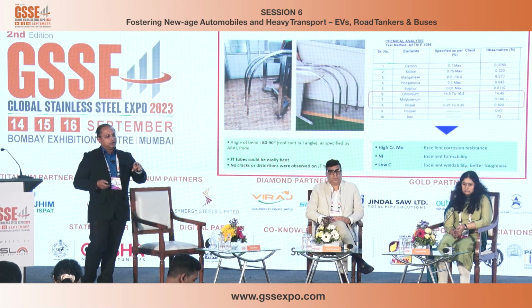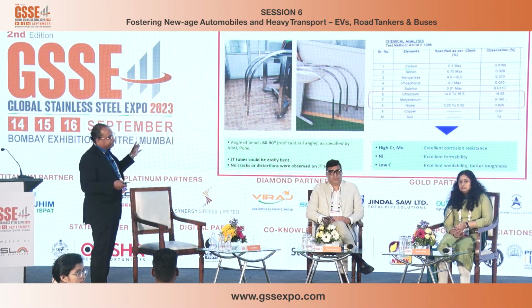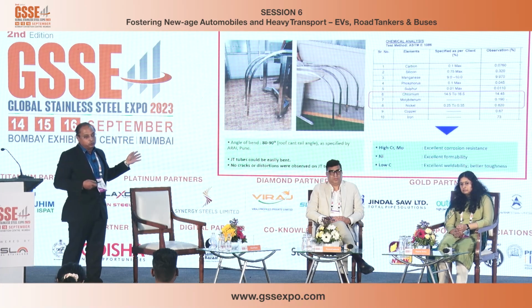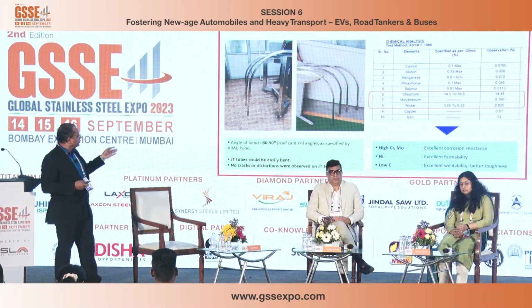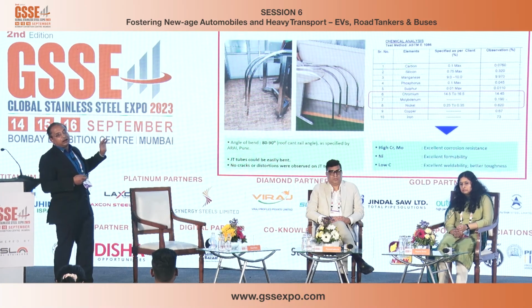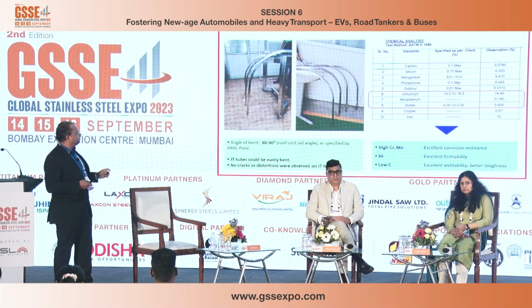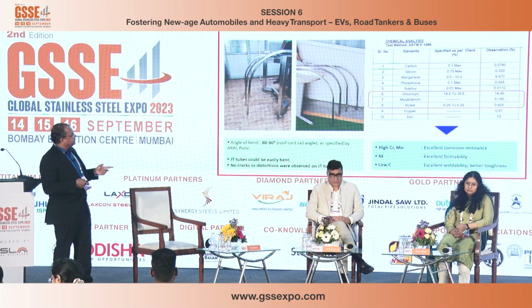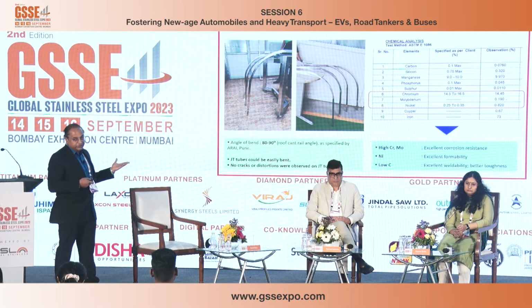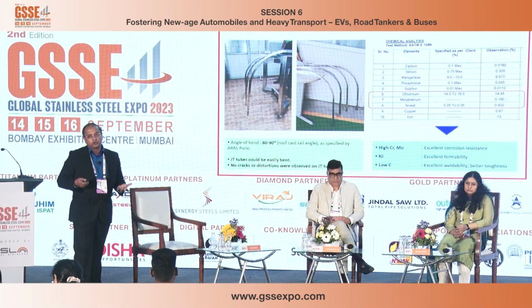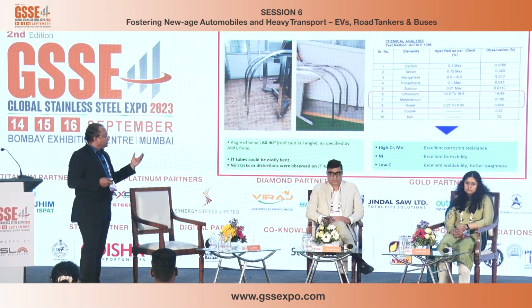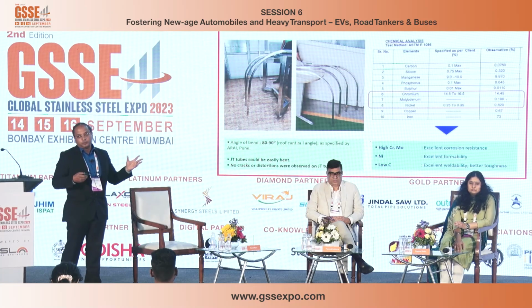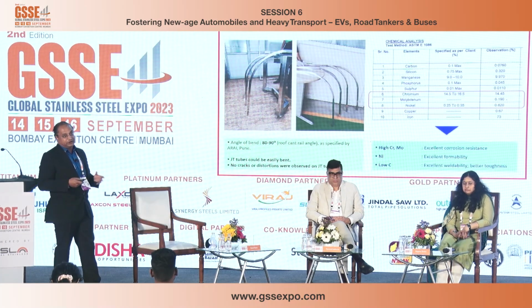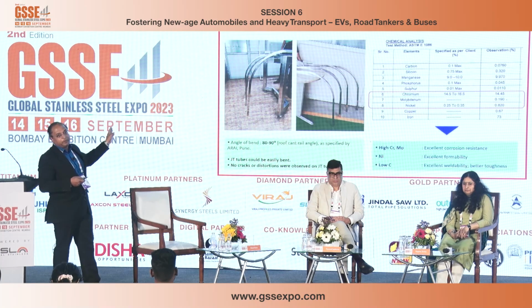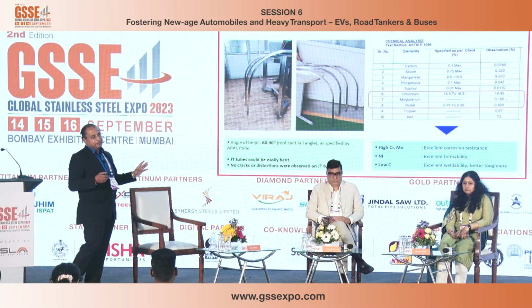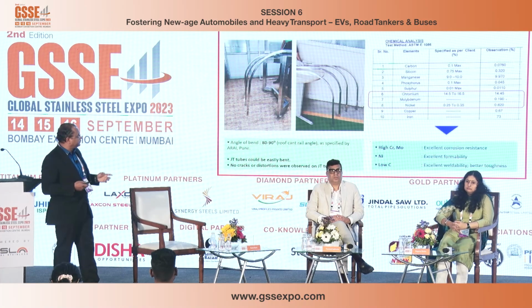And these tubes, as you can see in the photographs on the left, in fact, this is what ARAI had asked us to do. They asked us to conduct some bending trials. So we bent all these tubes, and none of them cracked. There was absolutely no issue in terms of bending. If you look at the chromium content, they have got a high chromium and high molybdenum. So both these impart very good corrosion resistance to the material. The nickel content is about 0.8, 0.9. So the formability is excellent, and therefore that's the reason why, even if you bend it at almost 80 to 90 degrees, there is absolutely no issue of cracking of the material.